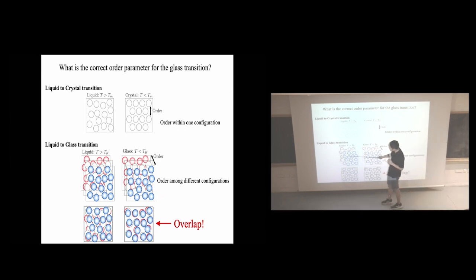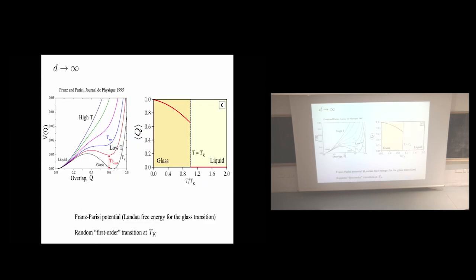On the liquid side, above the Kauzmann transition, if you prepare many configurations, all of them amorphous, but if you compute the overlap, they are very different because the liquid can explore many different configurations. Whereas in the glass state, if you compute the overlap, they are very similar because the system is stuck in one metastable state. Therefore, the overlap is the correct way to look at the glass transition. Okay. So now we have an order parameter for the glass transition.